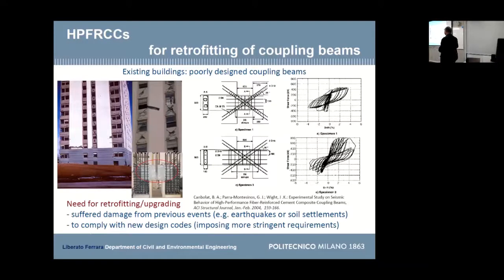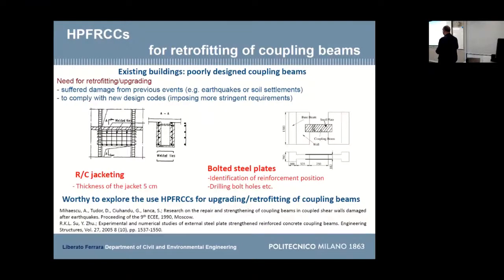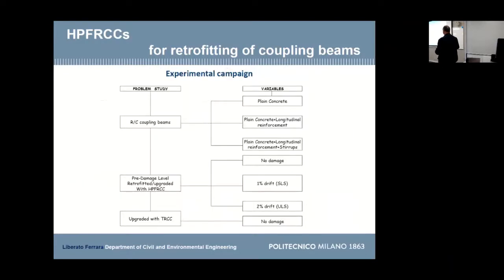Those in the picture are in Alaska, where a project was made. So you see, using these materials, you go from this kind of detailing, which is very demanding, to a less complicated detail. You use less reinforcement and you get the same capacity, or even better, because here we are at about 450 kilonewton, and you go here higher, and the cyclic capacity as well is okay. Well, if you have to upgrade a structure to retrofit it, you have different technologies. So we wanted to use this high performance material.